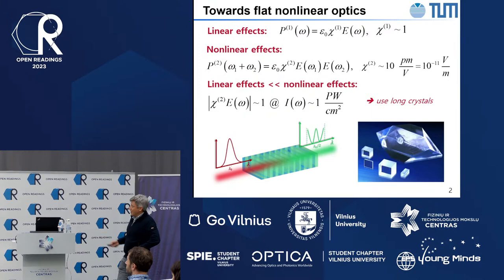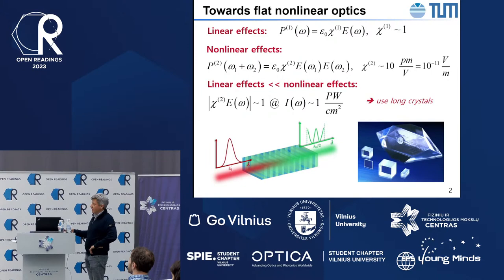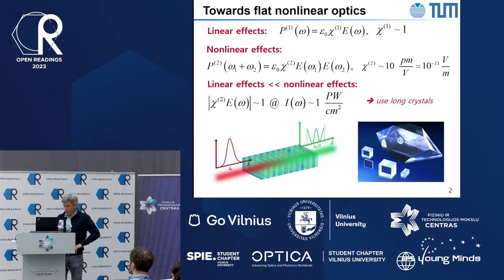And that gives you light intensities in the range of 1 petawatt per square centimeter, which is clearly a very high level of intensity, only available with pulsed lasers, and the material damage threshold is well below these levels. In fact, the electric field strength for these intensities is comparable to the atomic fields. And of course, materials cannot sustain this type of intensity.